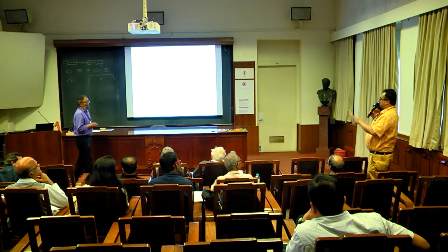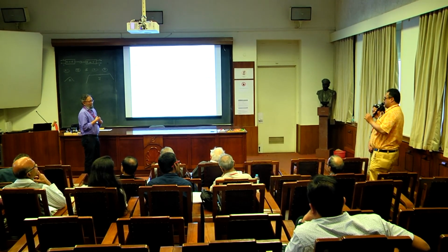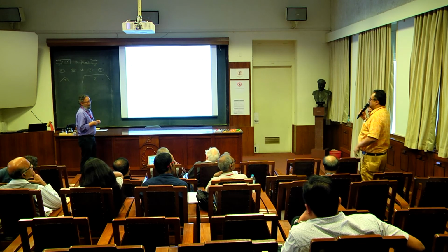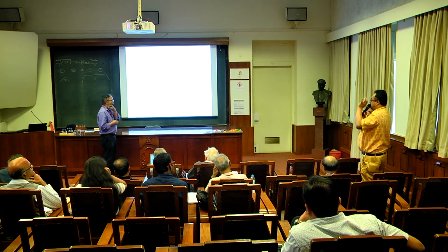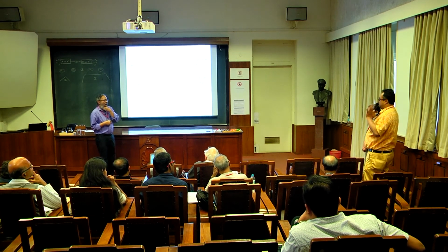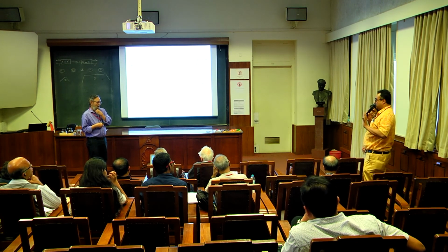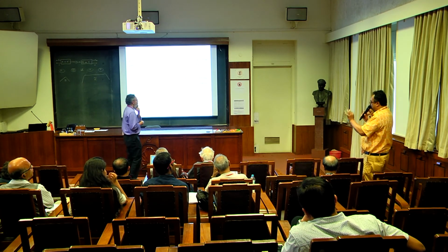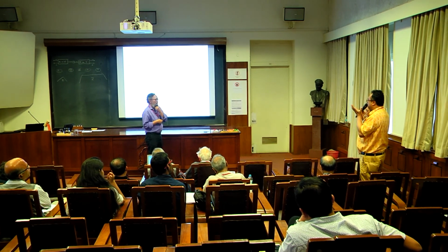So I have a conceptual confusion here. You started with this model which was motivated by the vortices and this Bitter decoration pattern where you have dislocations, yes, or rather lines. Nice, yes. If you believe in Larkin-Ovchinnikov theory of collective pinning, then the ordered vortex lattice is the one which is very weakly pinned, and the disordered vortex lattice is where it gets much more strongly pinned, provided your columnar pinning are randomly placed. Which means that wherever you have this grain boundary, you have an amorphous, well-pinned vortex lattice. Why should that be a liquid? It's an amorphous solid which does not have a dynamics.